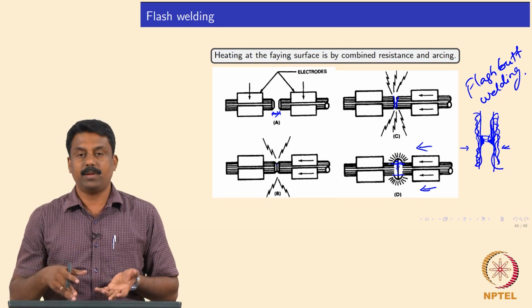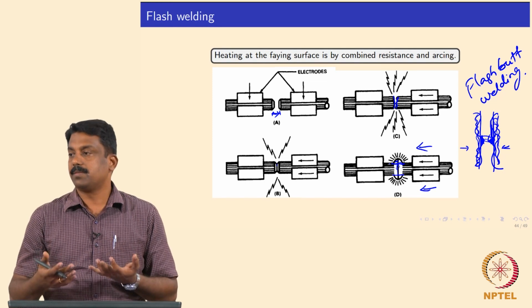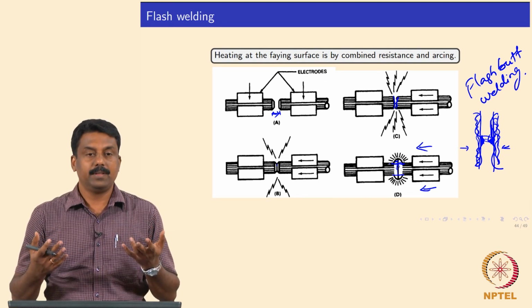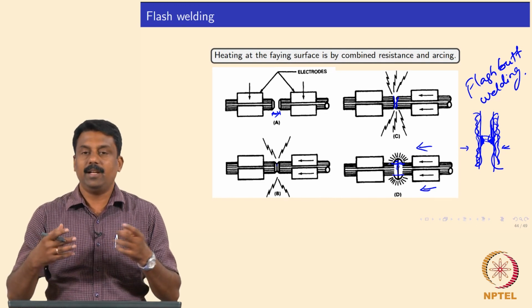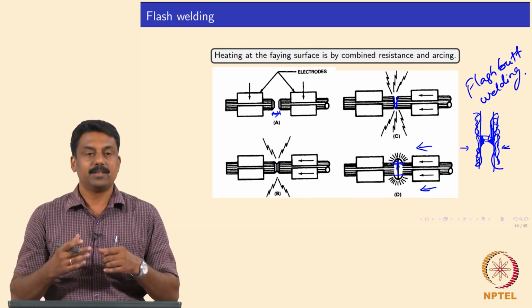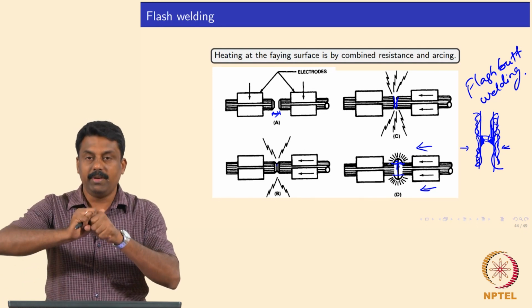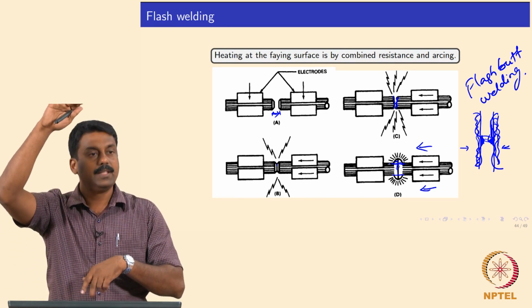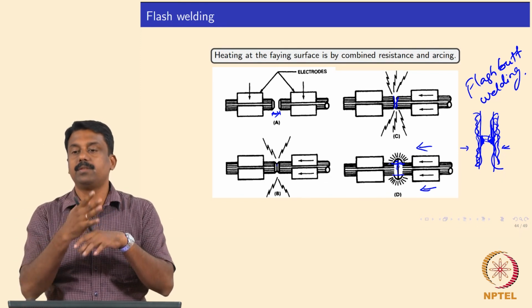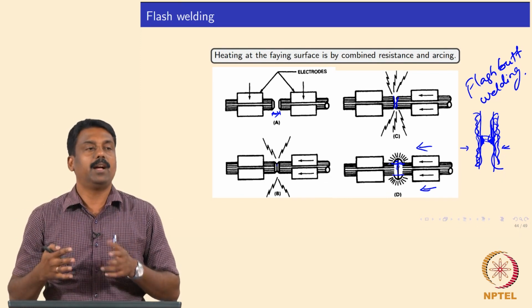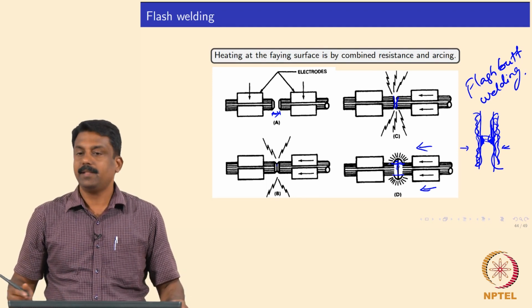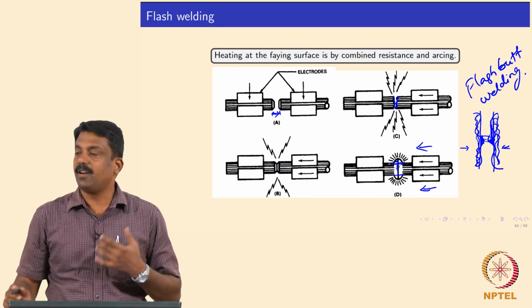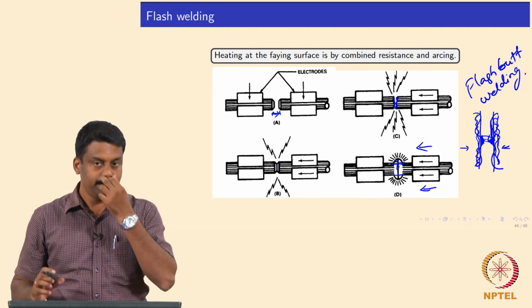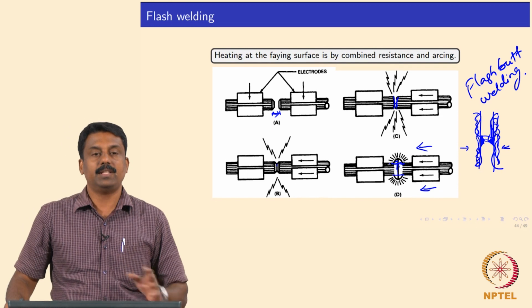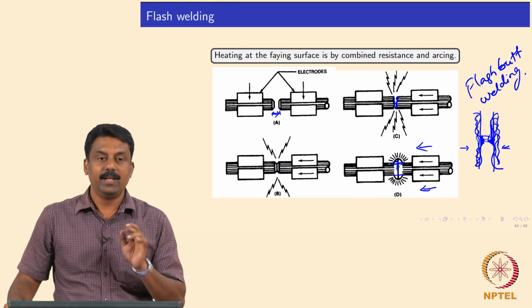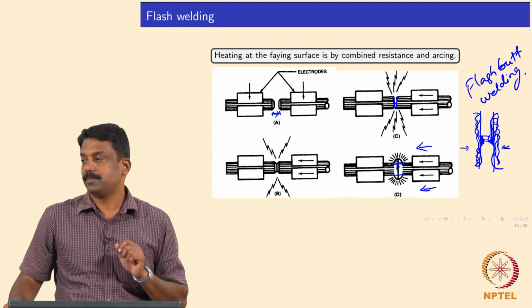And this is an extremely user friendly process, and a very robust process, because the arc heats up and melts the interface, but liquid would not form a joint. So you upset it so that liquid is splashed out at the circumference, and then the mechanical deformation would lead to the coalescence of the interface, forming a weld joint. Yes, clear? This process is very commonly used to make wheel rims. Almost 99% of conventional wheels are made with flash butt welding.